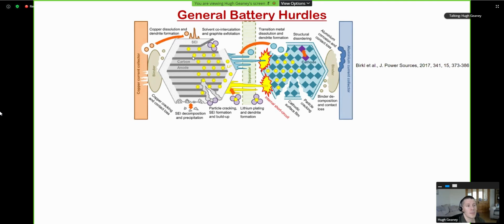This is probably the most stable, or one of the most stable, anode materials that we can have. But even then, there can be issues with the graphite. You can have particle cracking. You can have what's called SEI formation. I'll show an example of that in a second, where it's unstable, it breaks down and precipitates, like here.